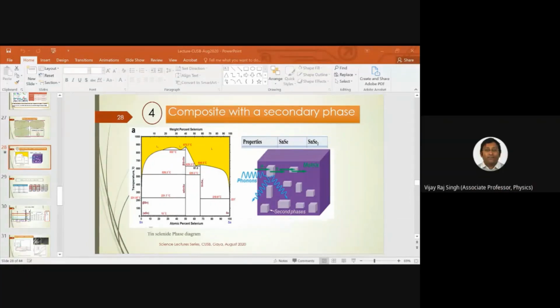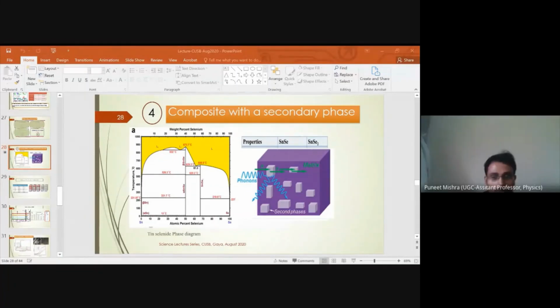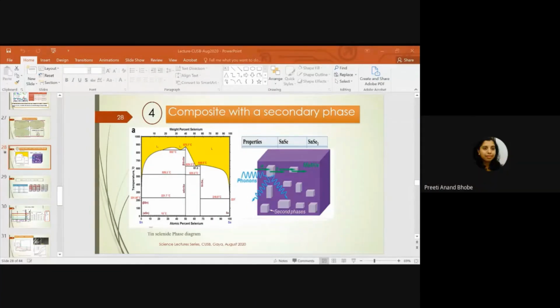You mentioned that the thermal conductivity has two contributions, one from phonons and one from electrons. Is it possible to measure and quantify them separately? No, it is not measured separately. It is measured in total, and then you separate out the lattice part from the electrical part, because the electrical part of thermal conductivity is related to electrical conductivity by the Wiedemann-Franz law. The ratio of thermal conductivity to electrical conductivity should be the Lorenz number, L. You use that relation and subtract out the electrical part. Whatever is left is your lattice part.